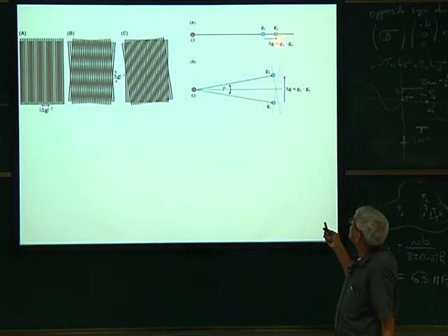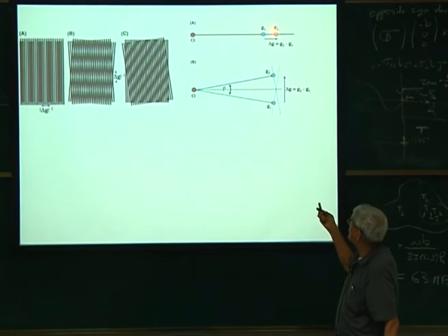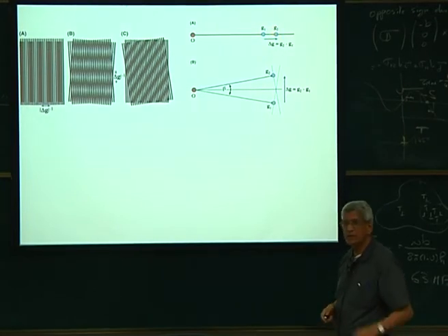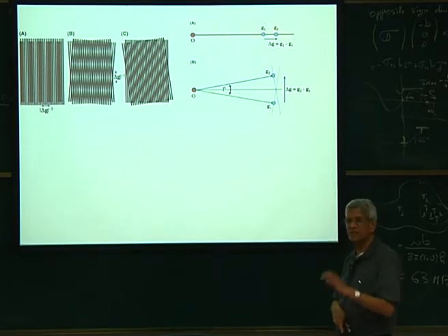The other lattice, with a lattice parameter just below it, will give a diffraction spot at another distance. If you put an aperture around both of them, in the image the fringes corresponding to both will interfere and give an interference pattern.